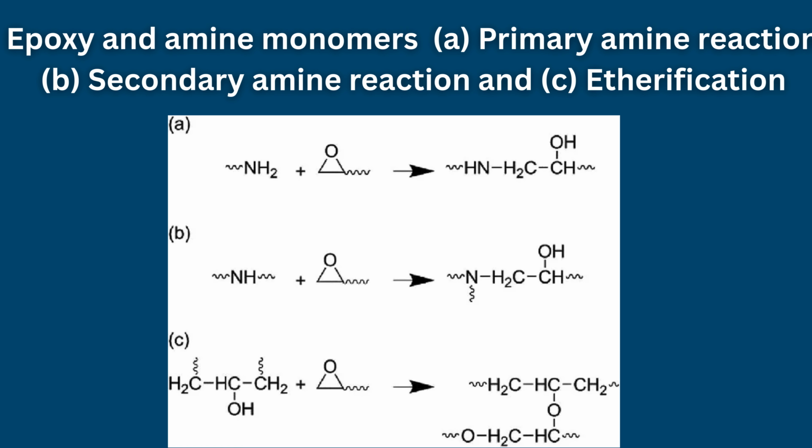Epoxy systems cured with aliphatic amines typically exhibit good resistance to moisture and solvents. They also demonstrate moderate thermal resistance, with heat distortion temperatures generally ranging from 70 degrees Celsius to 110 degrees Celsius. Short-term exposure of adhesive joints to temperatures approaching 100 degrees Celsius is often possible without severe degradation. Elevated temperature curing can improve the properties of aliphatic amine-cured epoxies. Higher curing temperatures promote greater cross-link density, which enhances mechanical strength, chemical resistance, and high-temperature stability.